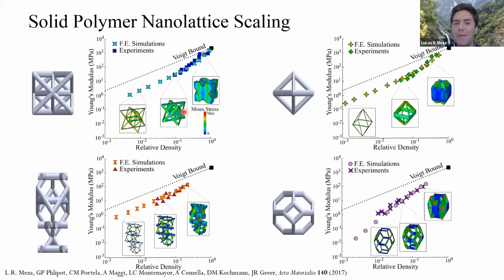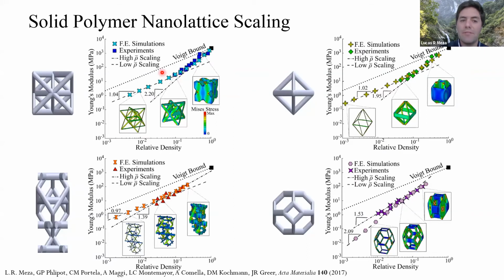It's a combination of beam and node structure. At very low relative densities, you get to that theoretical scaling you're supposed to have, but at high densities, you don't. In a practical sense, it's very difficult to make structures much lighter than 5-10% relative density, because they start collapsing onto their self-weight. Any sort of imperfection can lead to catastrophic failures. So this was a problem.